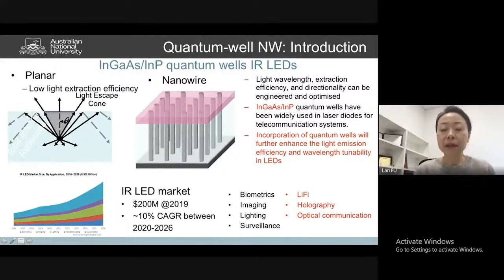But if we have a nanowire, we have a lot of space here, right? So the light extraction efficiency can be tuned by changing the spacing of the nanowires, as well as their diameters. By changing the design of the nanowire array, we can effectively tune the light extraction efficiency. In fact, we've done some basic simulation which showed that in a properly fabricated and designed nanowire array, we can achieve 70% light extraction efficiency. Also, as I said, if we implement quantum wells inside a nanowire array, we can also have the quantum confinement effect and bandgap engineering, which will also be very important, right?